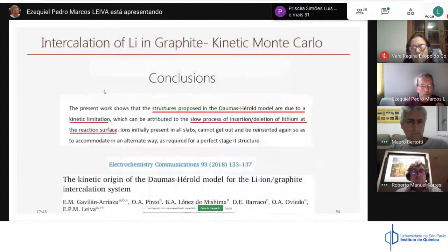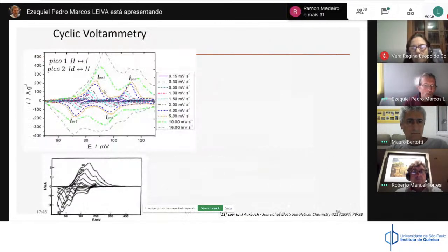So when you go to that, this is the peak. If you run faster and faster, these peaks merge together, but if you go slower and slower, you get the peak for phase 2 and the peak for phase 1 for the formation and the dissolution. So this is a voltammogram for the formation of phase 1 and phase 2, and this is what we get from the model.